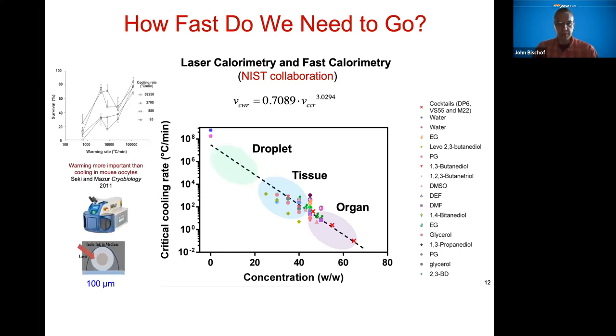One interesting thing that really caught our attention and has really been capturing the field of cryobiology for the last 10 years is that if you are able to reach these really, really fast rates, and Peter Mazur was one of the first, I think he was the first to do it. He was using pulsed near infrared lasers that would be absorbed by India ink. India ink is just a broadband absorber. And what he showed in mouse oocytes and other systems is that there's a forgiveness on the way down in terms of the cooling rate if you can come back with a really, really fast warming rate. These are giving us more and more clues as to what's forgivable and what's not, where the exact failure modes are, and what the critical rate limiting issues are for bringing vitrified systems back.